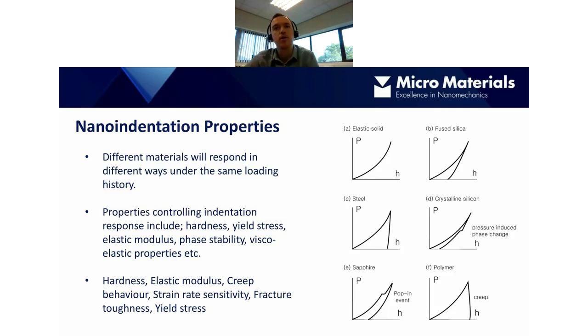We can also, with a nano indenter, detect these small changes in the structure of certain materials. So for example, if we perform a nano indentation into silicon, then we often see these small steps in the curve, which are pressure induced phase changes. These can be on the order of 5 or 10 nanometers in magnitude. Okay, so it really does require a very precise and sensitive nano indenter to detect these features. And similarly for sapphire, we get what are called pop-in events during the loading.